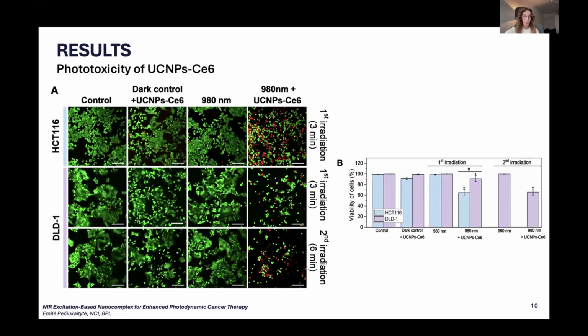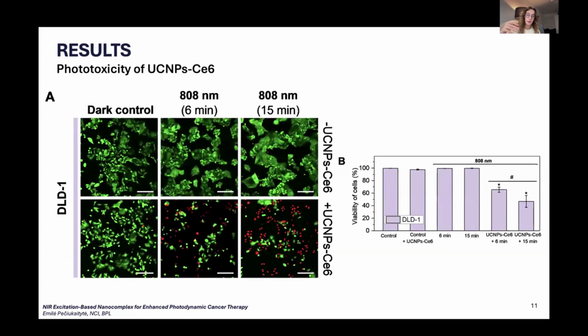Because DLD1 cells are more resistant and 808 nanometer excitation avoids photothermal effects, an extended 808 nanometer irradiation was also tested. And as we can see, viability decreased to 66% after 6 minutes, and even further to 47% after 15 minutes of irradiation, again with pronounced morphological cell changes. So to conclude these results in one place,